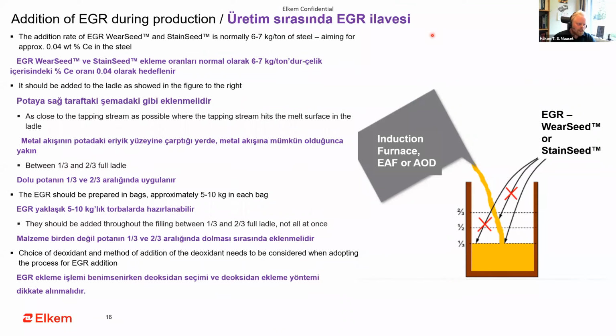So then we will look a little bit into how we actually add EGR during the production of steel. Well, the addition rate of EGR wear seed and stain seed is normally 6 to 7 kilograms per ton of steel. What we aim for is approximately 0.04 weight percent of cerium, or 400 ppm of cerium in the steel. And the way we add the EGR into the steel is very important to do correctly. Typically, the addition of EGR is something you do just before casting.